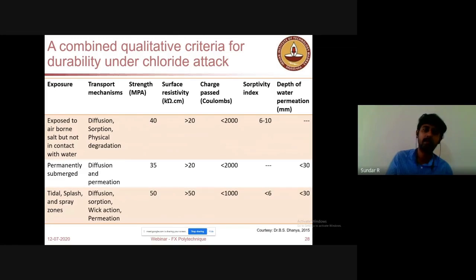So when you have a concrete in a permanently submerged condition, you should be able to define a strength criteria, which should be a minimum strength that should be used, and also we should have some 3 to 4 durability indicators which the concrete placed in a permanently submerged condition must adhere to. So when you are executing a concrete in such a condition, you should be considering all these numbers. When you do a test after a sufficient curing period, or after 1 or 2 years of inspection, the concrete at the site should have this amount of performance which is expected to give an intended